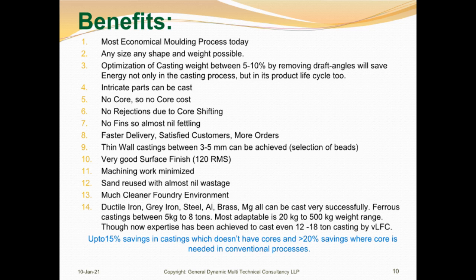Thin wall castings between 3 to 5 mm can be achieved. Very good surface finish, 120 RMS. Machining work is minimized. Sand is reused with less than 2% losses. Much cleaner foundry environment. Ductile iron, grey iron, steel, aluminum, brass, Mg all can be cast very successfully. Ferrous castings between 5 kg to 8 tons. Most adaptable is 20 kg to 500 kg weight range. Though now expertise has been achieved to cast even 12 to 18 ton castings by VLFC.